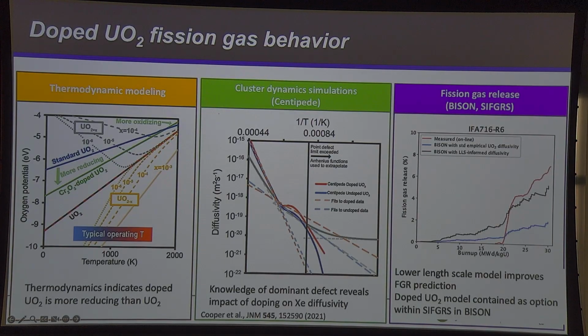But even for light water reactors for UO2, people are changing the fuels. They're putting dopants in to get better performance, in particular larger grain size. Now, that dopant could affect properties. And with the models that we're developing, we can make a statement on adding that dopant, how much does it change properties. And we have shown that by doing so, you can actually reproduce better experimental data for these advanced fuels than a model that doesn't go through all the sophisticated steps that we did.